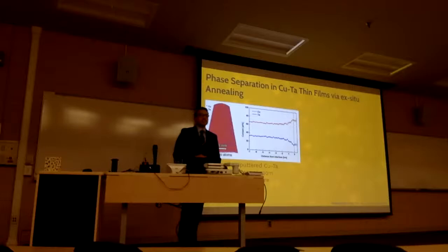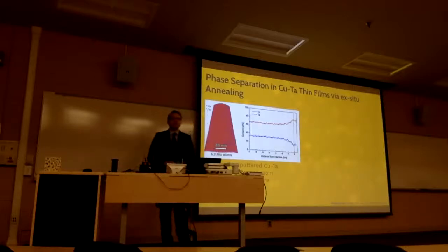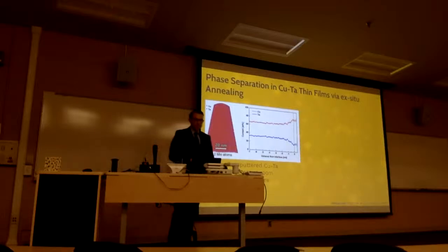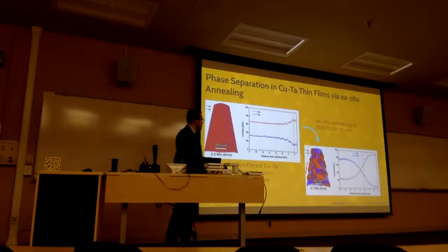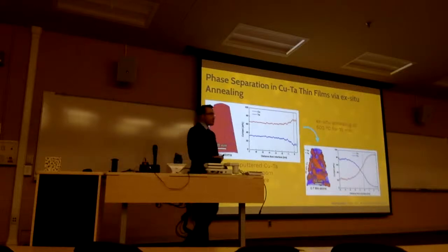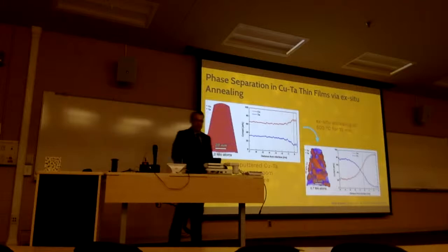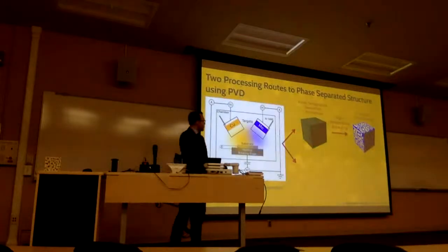We've actually seen this in the literature. So this is an example of a co-deposited copper tantalum system where the alloy at room temperature is homogeneous in the atom probe study here. We give it some temperature, and you can see that by adding temperature, we form this bicontinuous-like morphology for the copper and tantalum system. So you might be saying, well, that's great.